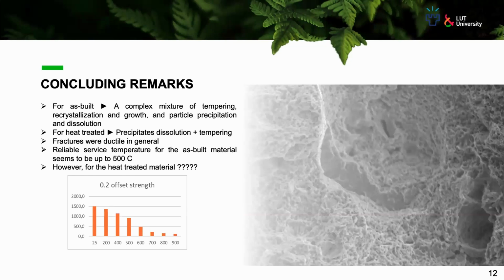For the as-built material, it can be used up to 500 degrees if we consider the strength of the material as our criterion, as it is recommended in many marketing, of course, data sheets. However, considering the smooth decline of the strength for the heat-treated version, defining a safe temperature might be a little more arduous.